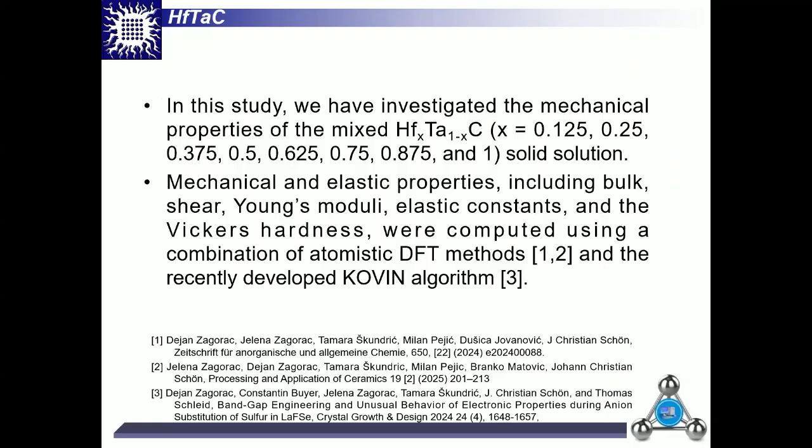In this study, I want to show you what happens when you mix hafnium and tantalum carbide. These are the mixtures: if you have 12.5% of hafnium, then you have 87.5% of tantalum carbide, then 25% of hafnium, and so on, up to 100% of hafnium or 100% of tantalum. We investigated mechanical elastic properties, which include bulk modulus, shear and Young's moduli, elastic constants, and Vickers hardness. This was done in combination of atomistic DFT methods on one side, and on the other side we invented a new method. I will say just a few words; the references are there if you're interested.